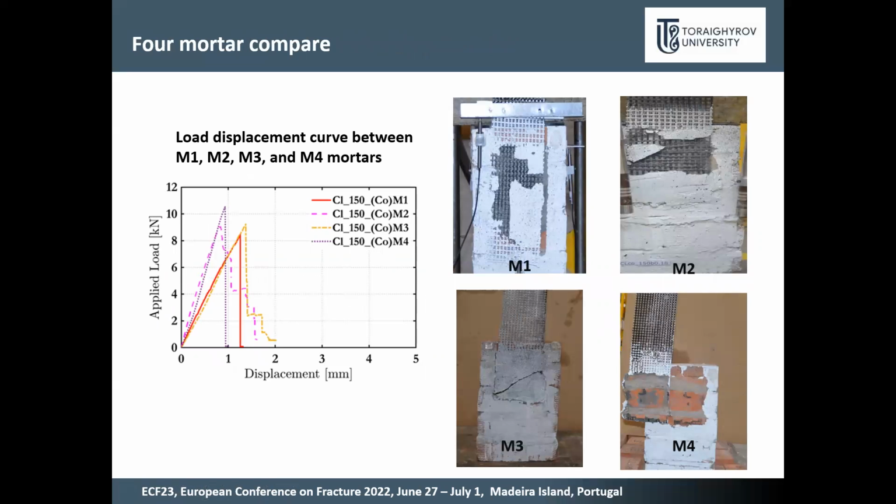Okay, and when we compare M3 mortar, just to remind you, it's an in-house made high performance concrete mortar, we have a sliding of the textile, and the textile was cracked, and the detachment worked only partly, and again after that the remaining part can still resist the load.